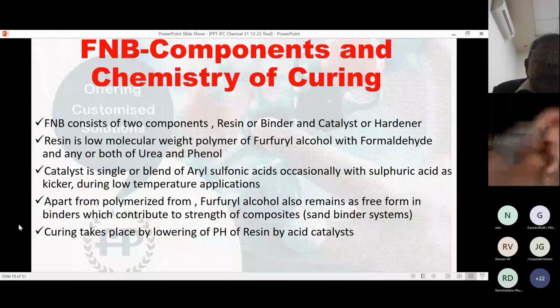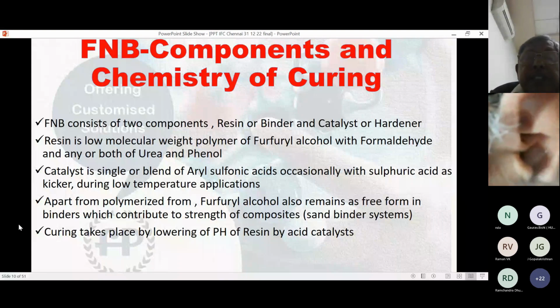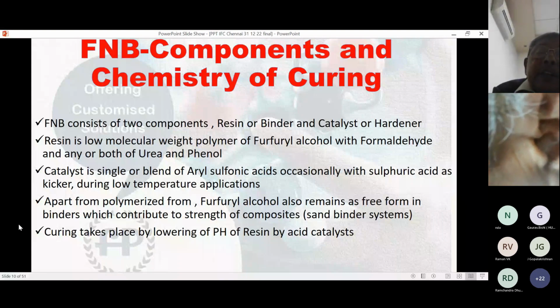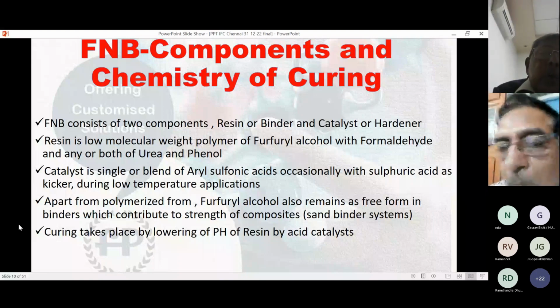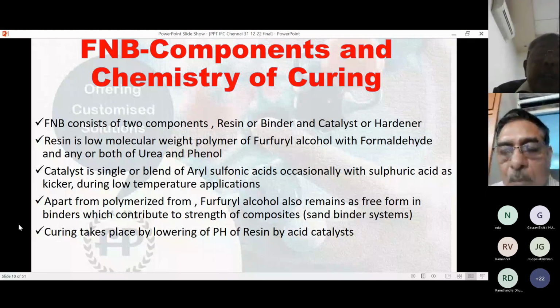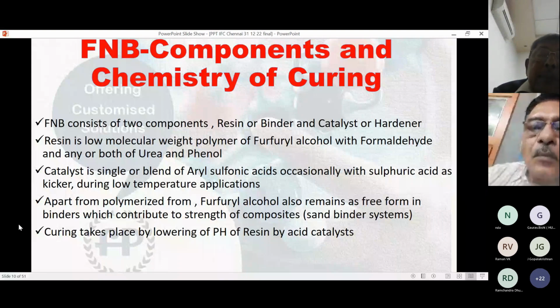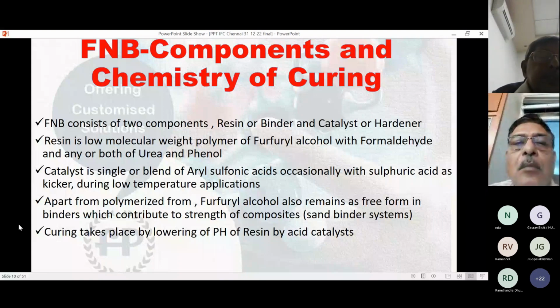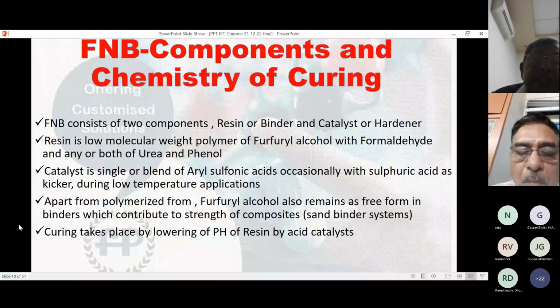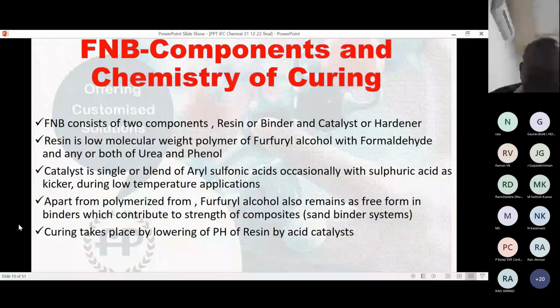But it is beyond the scope of this presentation why all acids cannot be used, like nitric acid, sulfuric acid, hydrochloric acid, because these don't give the required bench life with the mixed sand. They give uncontrolled reactions. So the curing mechanism of this is that Furan resins are not stable below a particular pH. So it is by lowering the pH of the resin that its curing takes place.